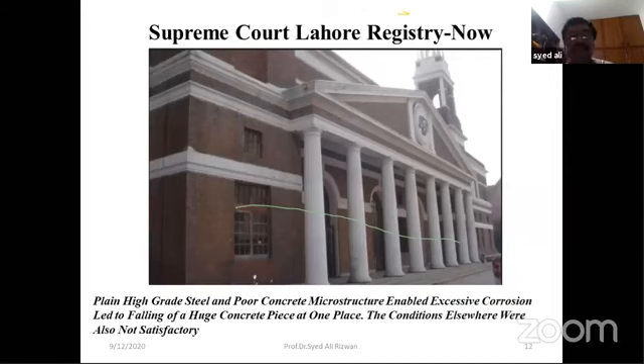So when we reached there, we saw it was a plain high-grade steel and very poor concrete microstructure. When the concrete microstructure is very poor, you will see sagging, some honeycombing at some locations. Then the CO2 in the environment can reach the pore solution, and then corrosion can start. So we estimated the thickness of the corrosion also, and that was the reason for this structural failure, corrosion.